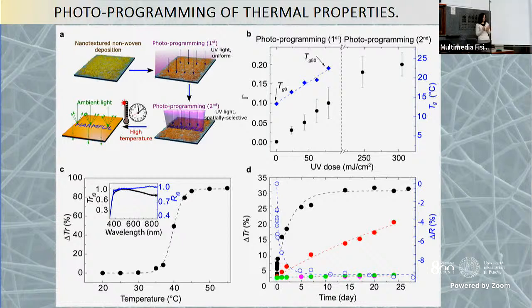The second step was a second photoprogramming, so a second exposure to light. In this case, we use a mask, so we expose some areas, some others not. And with this process, we are encoding a message in the material. But this message is a sign, and one can see the sign only if the device is exposed to appropriate temperatures, which means temperatures above the ones that we set in the first photoprogramming.